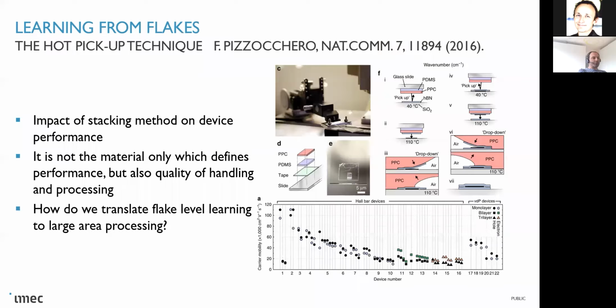You need to control the interface between the different flakes. There is a lot of knowledge there, even when you are doing flake manipulation, and you can only make high performance devices if you have full control of everything that's happening at these interfaces. And of course, this is the mirror that we need to keep in mind when we are trying to translate things to large area. So how will we avoid building in strain? How will we avoid dirt or uncontrolled deposition at interfaces, because all these things will have an effect on the performance of our devices.